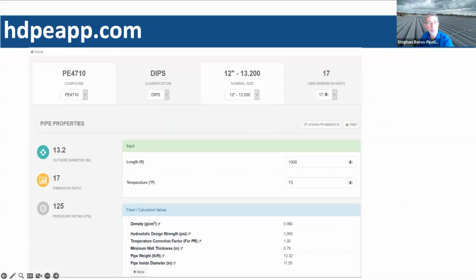So you go along the top of the pipe, you put in your sizing classification, IPS or DIPS, the nominal size of your pipe, and the DR of the pipe that you want to look at. Very initially, you just look at pipe properties. All right, what are my pipe properties down here? If you click on that More button, we can't do it here, it'll show you a whole list of pipe properties that are very helpful in your overall design rating. It'll show you DR17 at 73 degrees has a pressure rating of 125 PSI. That means it can operate at 120 PSI with flow up to probably 12 or 15 feet per second without having to derate that.